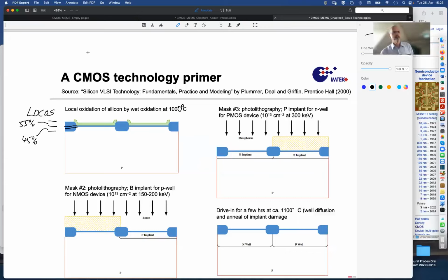So if I draw that in more detail, here we have our oxide, and here we have silicon nitride, and this is the silicon oxide, and down here we have the silicon. So the H2O molecules, of course, they will do their job down here to consume and let grow, but they also diffuse slightly underneath here. They diffuse everywhere, and it becomes just improbable for them to diffuse very far. But it means that there is also some growth occurring here, and then of course a lot here, which means that ultimately the silicon oxide layer will grow in this way, and the silicon nitride layer will have to give way to that growth. And this is a more realistic picture of what actually happens in this pretty sharp transition.